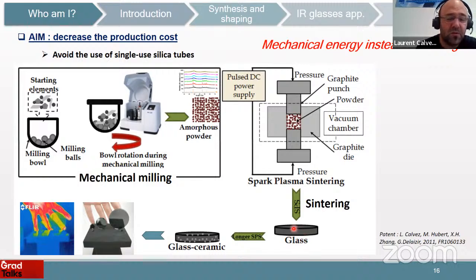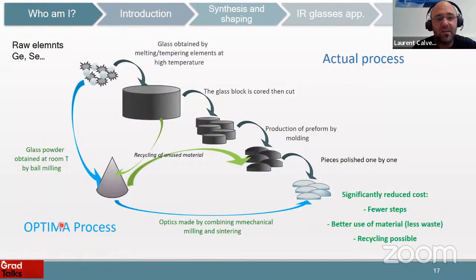And if you let it run for a longer time, you can also make glass ceramic. So I will talk about glass ceramic later. And here is a picture of what we've obtained: different glasses of different diameters. And using a thermal camera, you can see that it's perfectly transparent in the infrared. So this process was called the Optima process.